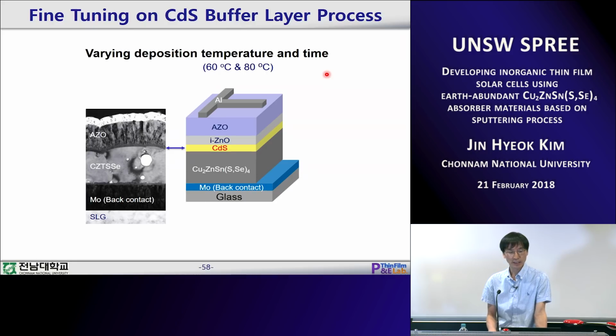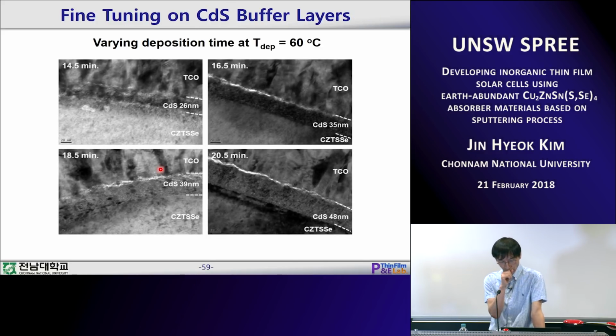And after that, we tried to control the cadmium sulfide buffer layer. This is a very thin layer, just above the absorber layer. To do that, first we fixed the temperature. Actually we did 80 degrees first, but I will show you the result at 60 degrees. At 60 degrees, we changed the deposition time from 14 to 20 minutes, and it gives a thickness difference of the CdS layer from 26 nanometers to almost 50 nanometers. So by varying the deposition time, we can vary the buffer layer thickness.